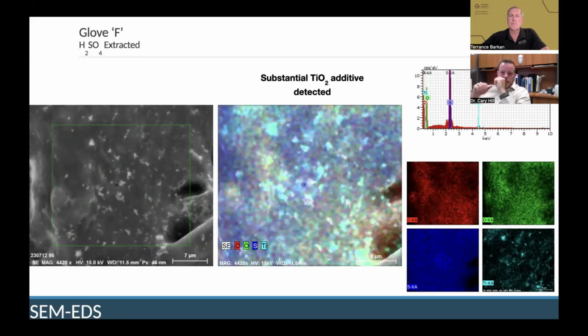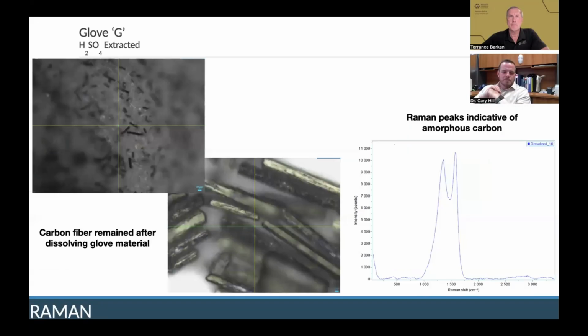And when I say this in all these slides, I'm not relying on just what I'm showing you here. I'm just showing you some of the highlights of what we found. We have other compositional characteristics that we analyzed to make these claims. And then in the next slide, we've got another glove that we analyzed more recently, which contained prolific carbon fiber. The material in the left image, that optical microscopy image, is after it's been dissolved. We just extracted the remaining material from the glove fibers with sulfuric acid and then filtered. And so you're seeing these bits of carbon fiber that are stuck on the surface of the material.